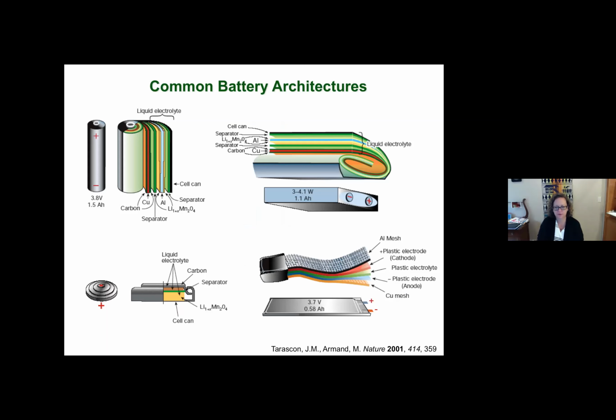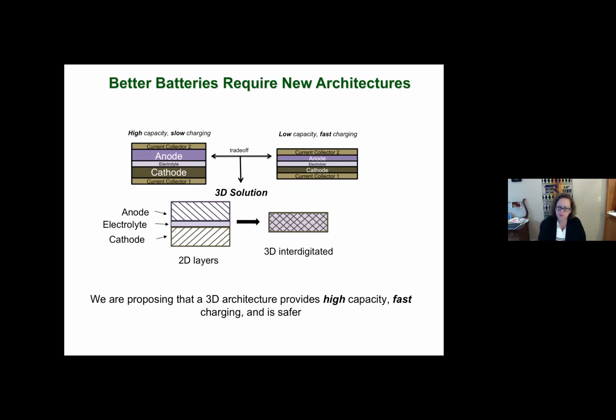I think you're all probably very familiar with this figure as well. What I'm trying to highlight here is all current battery architectures are what I call two-dimensional batteries. They're layers that either get stacked or rolled. And the challenge with this kind of architecture really is that if you want to increase the energy density of these cells, you make the layers really thick, and so then the power suffers. If you make the layers really thin, you can get high power batteries, but then the energy density suffers. And so what we would like to do is try to combine high energy density and high power density. And in my opinion, the best way to do that really is to make a 3D battery.